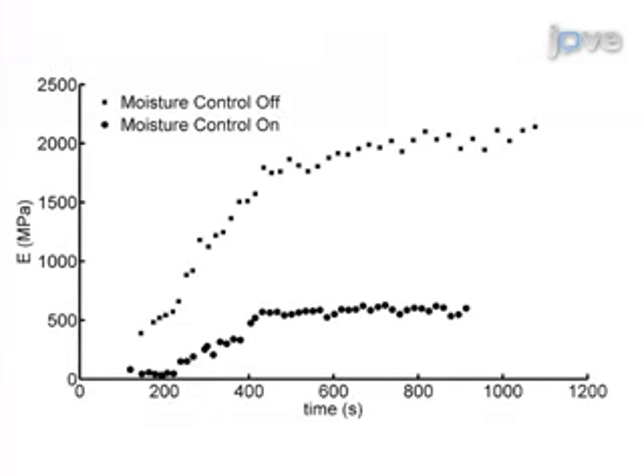Here is the Young's modulus versus time for water-saturated samples in both moisture-controlled and non-controlled tensile testing environments. The recovery of the initial Young's modulus is much slower in the controlled environment. This demonstrates the increase in the time required for the sample to dry in this environment. This extra time can be used to perform mechanical tests on samples that have been implanted.